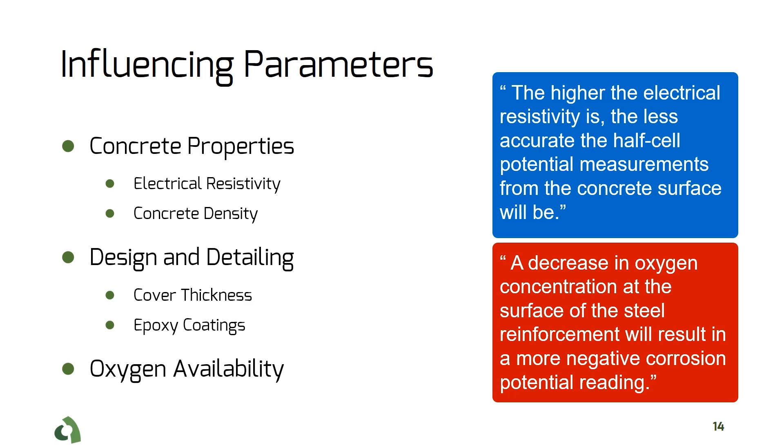When doing a half-cell potential test, one should remember that the surface should be free of paint and chemical epoxy coatings. Also, the test on stainless steel reinforcement and epoxy coated rebar will increase the chance of error in the measurements.